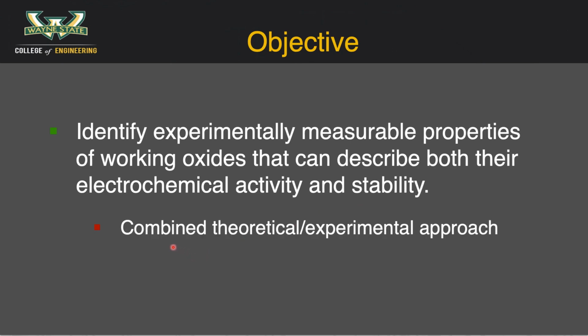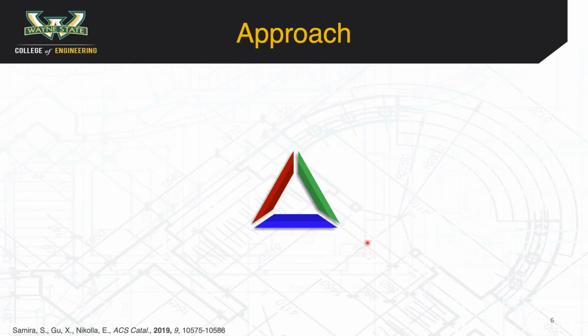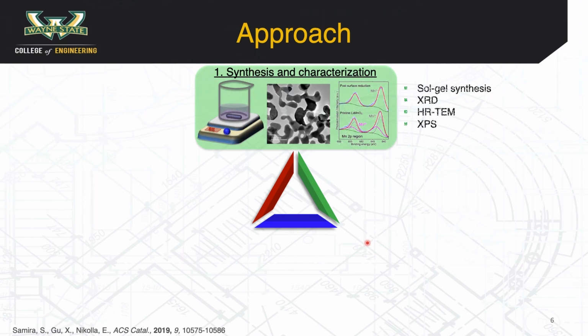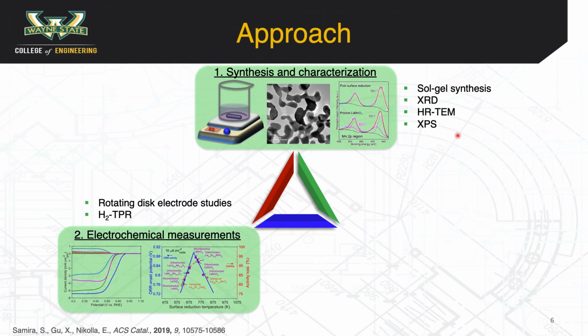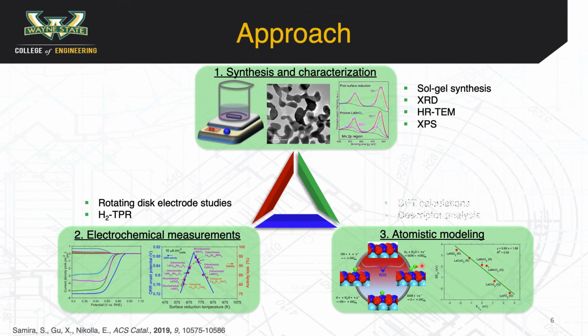We propose to combine theoretical and experimental tools to bridge the gap between the two. Our approach involves a correlated interplay between synthesis and characterization using some of the tools that are listed here, in combination with detailed electrochemical measurements and surface property measurements. These two are then used as a feedback loop into theoretical calculations using atomistic modeling and some descriptor type analysis.